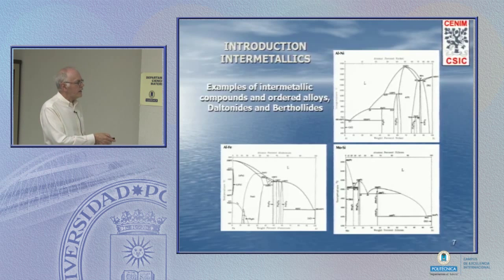If we contrast with the iron aluminide, here's iron aluminium. Here we've got the FeAl phase region, ordered up to about melting over a wide composition range, very much the same as NiAl. But in this case, at Fe3Al, we've got another phase which exists over a moderately wide composition range, ordered only up to about 550 centigrade. Then it disorders. And in the moly-silicon phase diagram, here we've got a couple of intermetallic compounds which are Daltonides. The chemical composition is very well defined, and they're very strong intermetallics, ordered all the way up to the melting point.